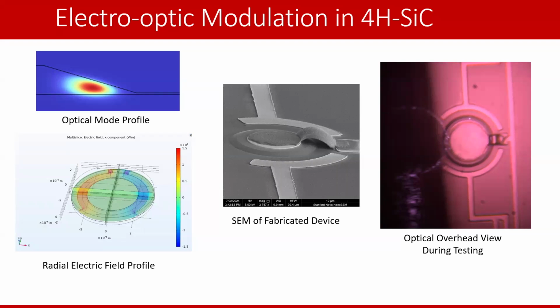And so if you put the metal contact where the waveguide is, you'll kill your optical mode, and you actually won't couple to the device. So you need to leave some region here open so that you can bring your waveguide in to couple to the whispering gallery mode resonator. And then you also need this little bridge here to get your center pin to the right potential, which means the applied electric field around the resonator is not radially symmetric. Because it's not radially symmetric, it makes some of the calculations a little difficult.